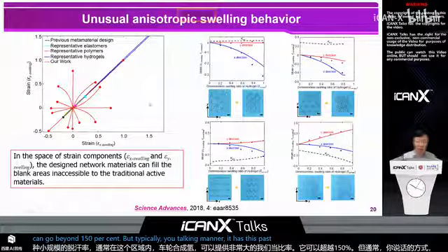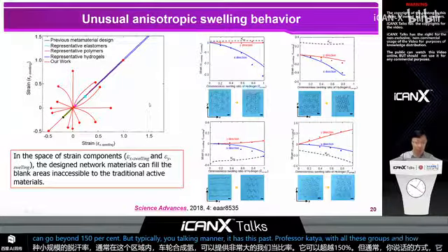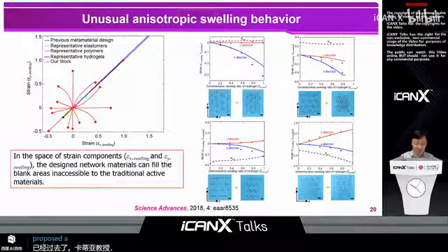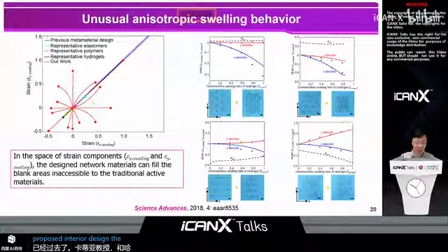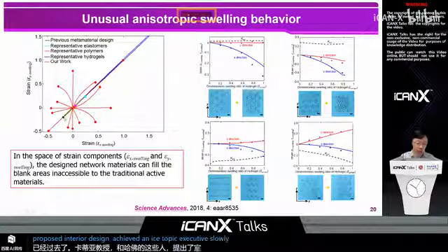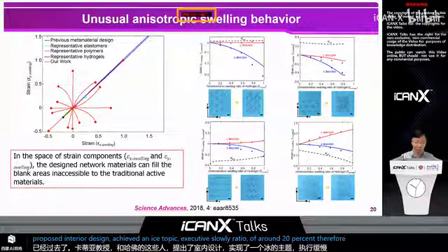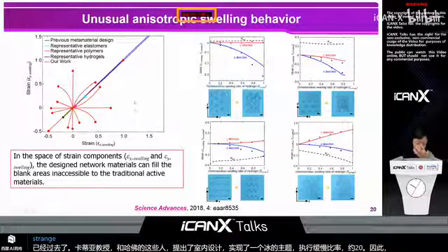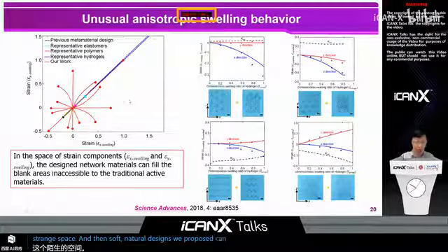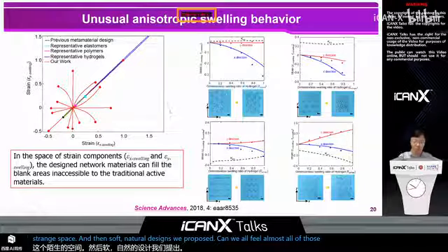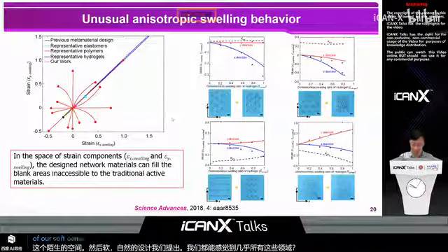Professor Katia Bertoldi's group at Harvard proposed a metamaterial design that can achieve an isotropic effective swelling ratio of around 20%. Therefore, there are many blank areas in this strain space, and the soft network designs we propose can well fill almost all of those blank areas. So this indicates the capability of our soft composite network design.